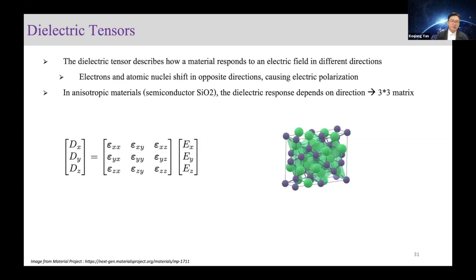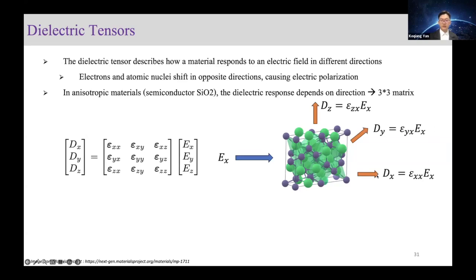So let's go into a little bit about the dielectric tensors. The dielectric tensor describes how a material responds to an alternating electrical field in different directions. The reason there are responses in the material structure is that if you apply an alternating electrical field, the electrons and the atomic nuclei will shift in different directions, causing some inner electrical polarization in the material. And if the material structure is anisotropic, the dielectric responses will depend on direction. For example, if we apply an electrical field in the x direction, there will be 3 responses in the structure, dx, dy, dz, where d is displacement. And to describe the whole response, we will need 9 values in the matrix to represent the dielectric tensor.